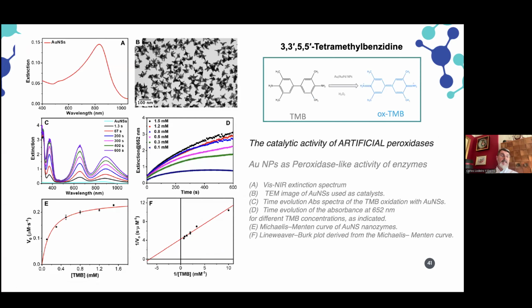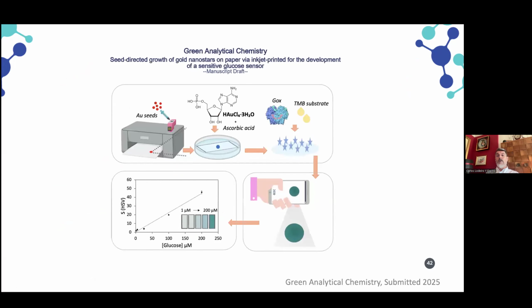This system was used, for example, for degradation of TMB, in which, in the presence of H2O2, which can oxidize the colorant, producing the ox-TMB product in which we observe the blue color, and this acts as a catalytic artificial peroxidase molecule. We observed one of the highest values for the Michaelis-Menten curve and for the Lineweaver-Burk plot, in which we observed a very high velocity and very high constants for a gold nanoparticle. However, it was not enough, and then we needed to move forward with this.